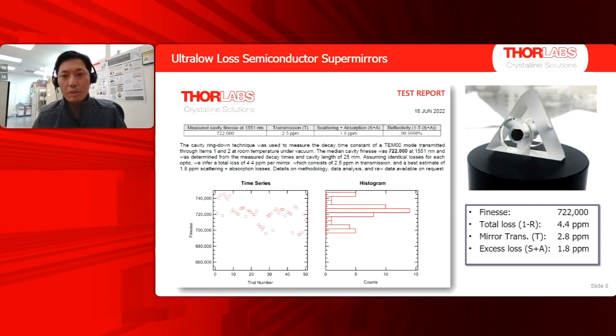So here's an example of a near-infrared crystalline supermirror cavity that we've made in the past. You'll see, again, there's that 1-inch glass substrate with the dark coating disc in the middle. There are actually 2 of those mirrors that are contacted onto that sort of triangular looking piece of glass that's known as a spacer. It simply holds the 2 mirrors at a very fixed distance apart.